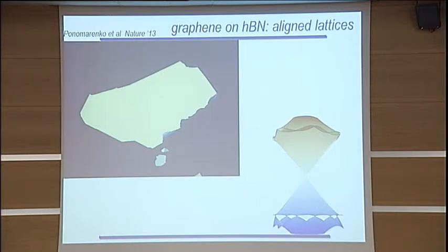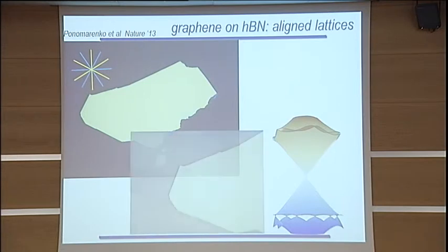in our experiment. For example, here is a crystal of boron nitride, and it's been noticed for quite a long time now that usually those mechanically exfoliated crystals would always have nice facets, and those facets are always lying at 60 degrees to each other, and half of them would correspond to armchair edge, half of them correspond to the zigzag edge. And now when you do all the transfers and arrangement of those heterostructures, if you take some care about aligning the crystals, so here is the, I'm not sure if you can see it